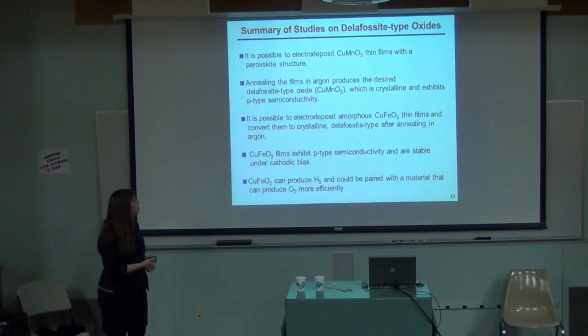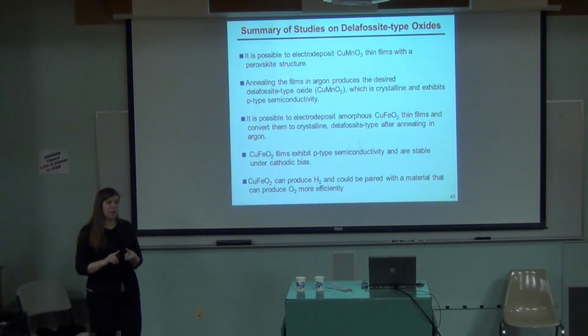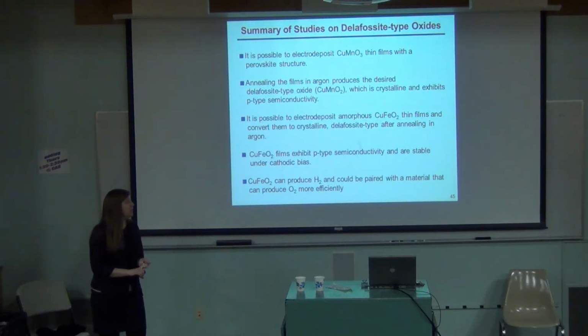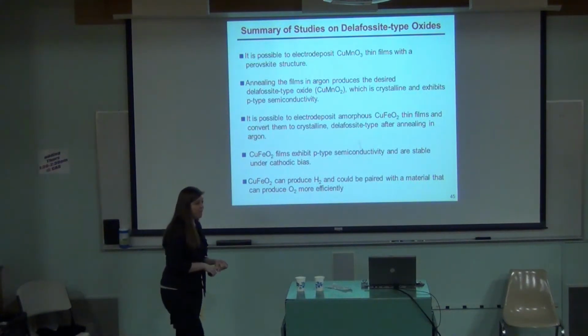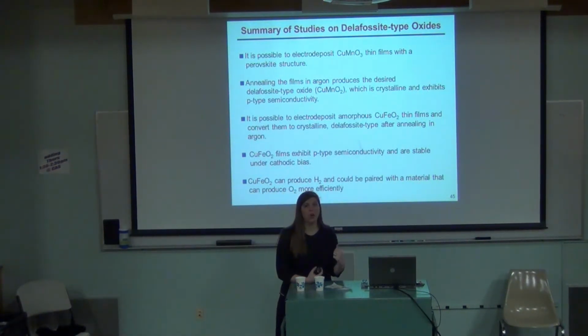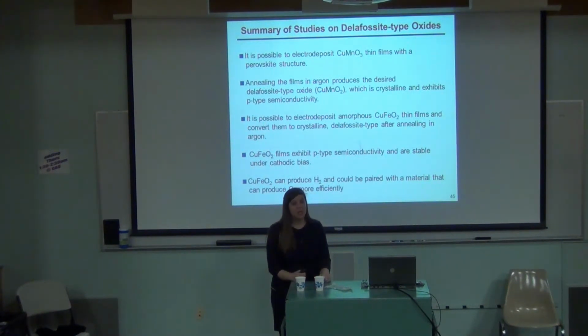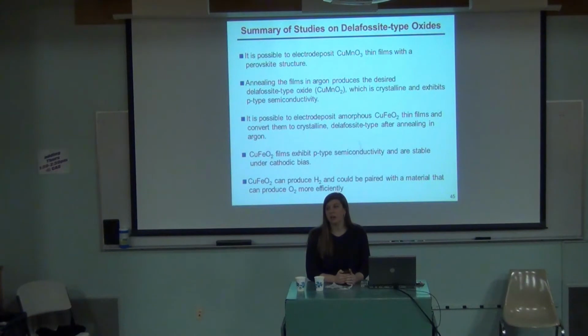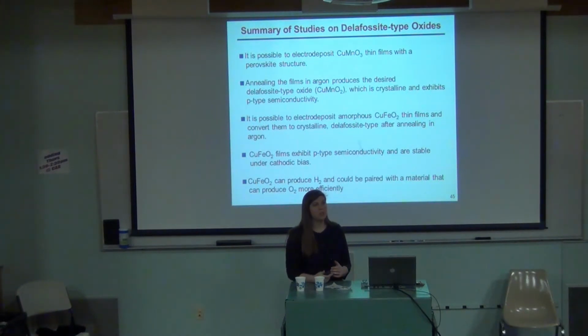So in conclusion for this part, you can both electrodeposit perovskite and Delafossite, and you can get p-type materials. And I didn't show it in this slide, but after I left, they continued on with the copper iron oxide, and they were actually able to detect hydrogen with a GC. So it does produce hydrogen. They had to do some fancy studies for that, and we ended up getting to publish that, but they had to purge it with a bunch of argon. They had to do a bunch of things to the system. So it's not that great, but like I said, there's a lot of room for improvement, and that's where we like science to have need for improvement.